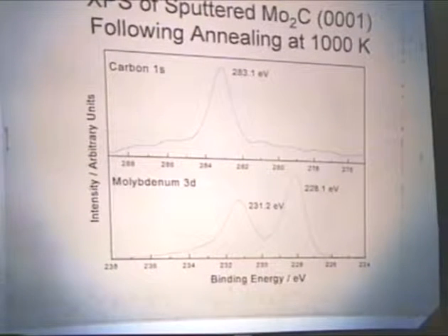The only surface contamination that we've been able to detect is oxygen, and through any combination of sputtering and annealing, we're not able to remove that. However, it is less than 2 atomic percent, so it's very small.